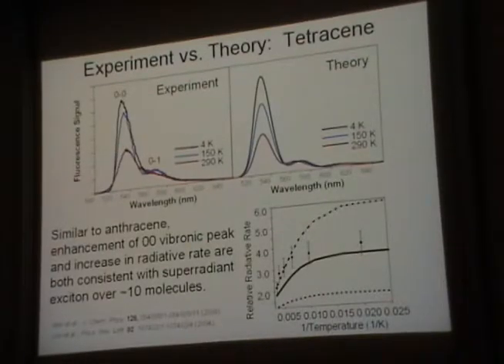And the nice thing is that once you have a theory that quantitatively describes the vibronic line shape, you can measure the vibronic line shape quantitatively. So here's experiment and here's theory at different temperatures, and you can see that 0-0 peak shoots right up. The nice thing about this data is it's not normalized, right? This is absolute comparison. We're not scaling everything to say the 0-1 peak to make it all look the same, okay? So 0-0 shoots up here, 0-0 shoots up here, down here. So this is one measurement, the line shape.